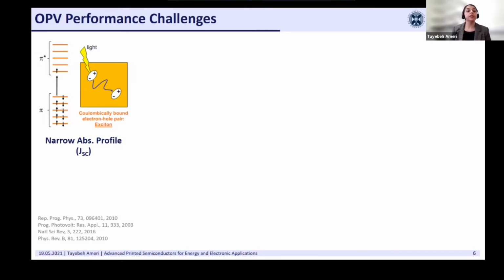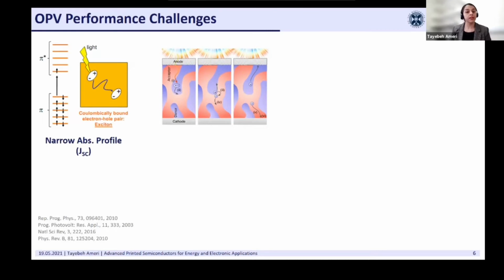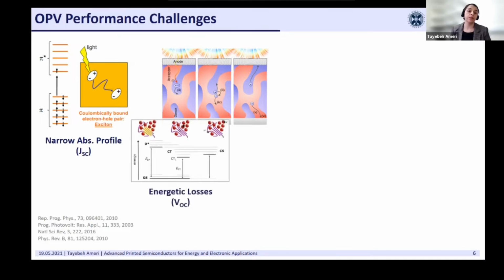The second point is that we need to introduce a second material with the higher electron affinity called acceptor to split this electron hole pair into free charge carriers to be extracted at their corresponding electrodes and produce electricity. At the interface of these donor acceptor materials, new states are formed called charge transfer states that indeed cause some energetic losses and reduce the open circuit voltage in our devices.